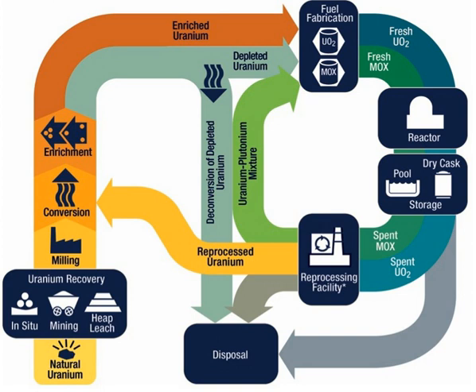For use as nuclear fuel, enriched uranium hexafluoride is converted into uranium dioxide powder that is then processed into pellet form. The pellets are fired in a high-temperature sintering furnace to create hard, ceramic pellets of enriched uranium, then undergo a grinding process to achieve a uniform pellet size. The pellets are stacked into tubes of corrosion-resistant metal alloy, sealed to contain the fuel — these tubes are called fuel rods. The finished fuel rods are grouped in special fuel assemblies used to build up the nuclear fuel core of a power reactor. Stainless steel was used in the past, but most reactors now use a zirconium alloy.